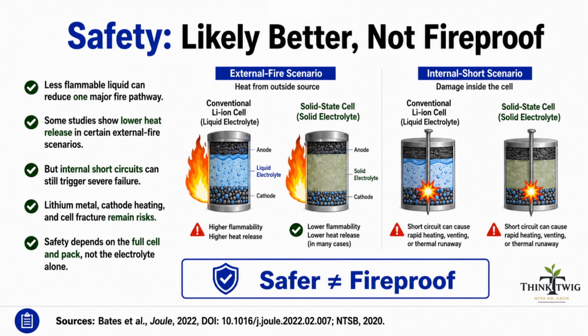But now change the failure. Imagine an internal short circuit. The battery still stores a large amount of energy. The cathode can still overheat. The lithium metal can still react violently. And some cathodes can release oxygen. The solid electrolyte can still crack. Once it cracks, lithium may find a path through it. So, yes, solid state batteries may reduce fire risk, but they do not remove every danger. The correct conclusion is simple: safer does not mean fireproof. The electrolyte matters, but the full cell matters more, and the complete battery pack matters most.